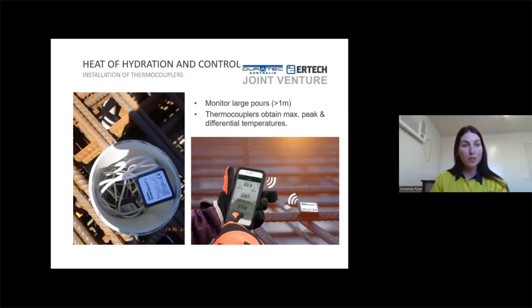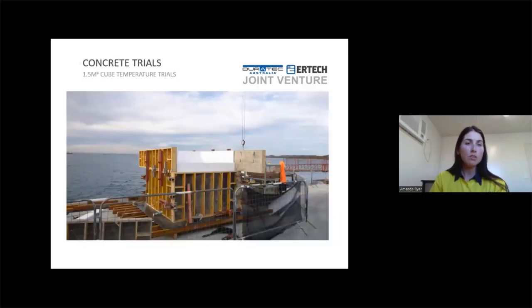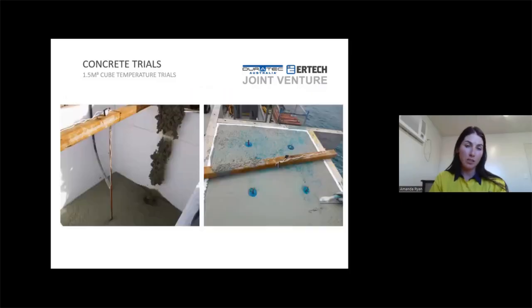With our pours, the specification requirement for the core of the slab was not to exceed 75 degrees Celsius, and the differential between the core and external surface not to exceed 25 degrees Celsius. So we did a couple of trials to ensure that we were going to achieve it. We did 3 trials in total, and we conducted them for large pours to determine the critical conditions met by appropriate measures of controlled heat in the concrete.